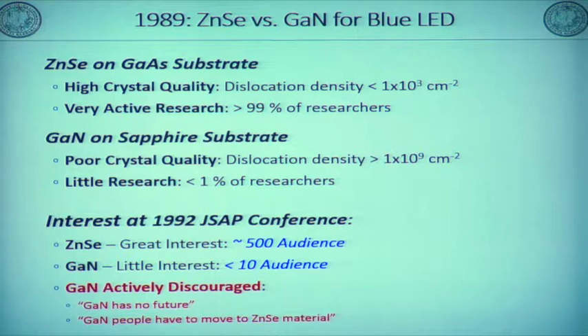So that's when I started the blue LEDs in '89. For zinc selenide on gallium arsenide, the crystal defect density is less than 10 to the third. So basically all of the scientists who worked on blue LEDs selected zinc selenide. That was '89. In the case of gallium nitride on sapphire, crystal defect is more than 10 to the 9th per square centimeter. And so not to 0, but only a few researchers were working in the world. In the United States, I think only 1 or 2 groups, and in Japan, 3 groups. In Europe, I don't know, maybe 1 group. So it's a small number of people.